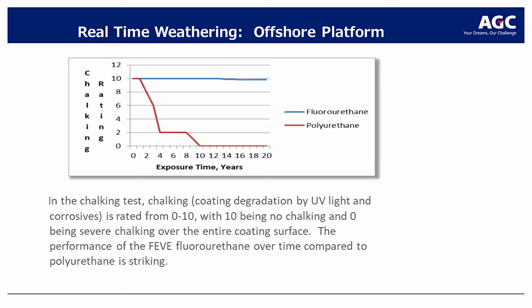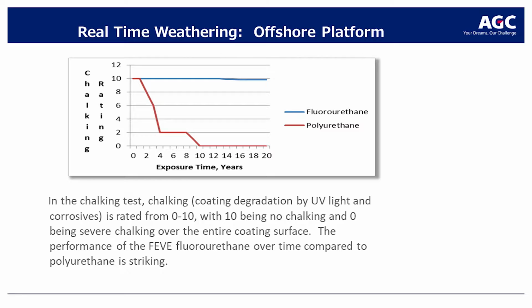There are standards. What they do is they compare the chalking on these test panels with the standards, and what you see is after about 10 years, the polyurethane is completely chalked. If it's, say, a red, that means the red will be faded. It might even be trending toward pink at that point. Whereas the FEVE coating after 20 years in this environment shows very little degradation.